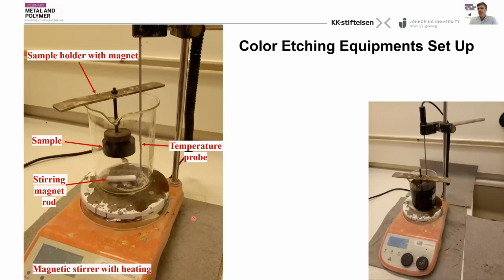Here is the color etching equipment setup. On the left, we can see that for the preparation of the color etching treatment, we need a glass container on a magnetic stirrer with heating. At the bottom of the glass container, we have a stirring magnet rod. Here you can see also a sample holder with a magnet, the sample at the bottom. And there is also a temperature probe that controls the temperature of the mixture and can adjust it automatically. Here on the right, we have the setup as it is in operational form when it's operated.